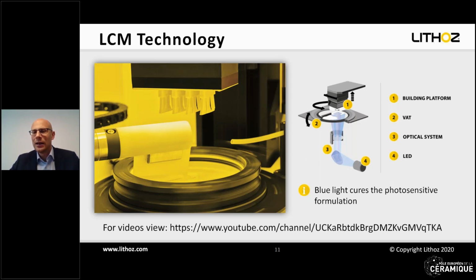Where the light hits the material, it solidifies, and then you build up the part layer by layer, as with any conventional forming technology. The advantage of this upside-down approach is that you can make very fine details, and also very thin layers. When you build up upside down, you have no contact between the blade and the part, and therefore it's unlikely that you destroy the part with the blade, which sometimes happens if you expose from the top.